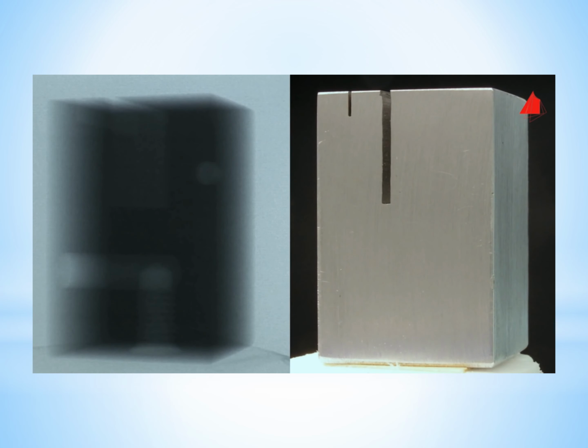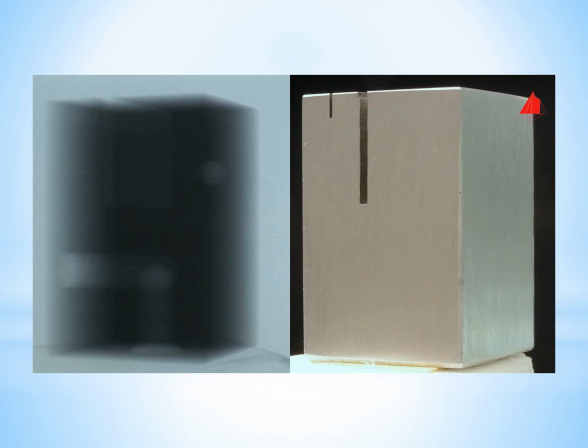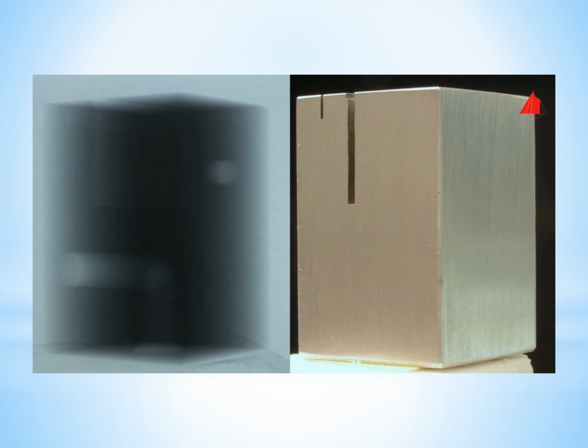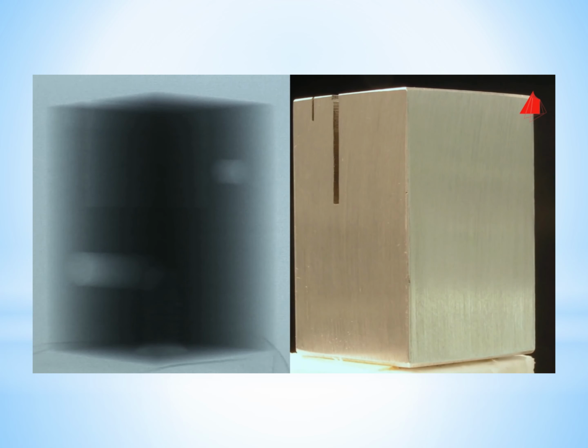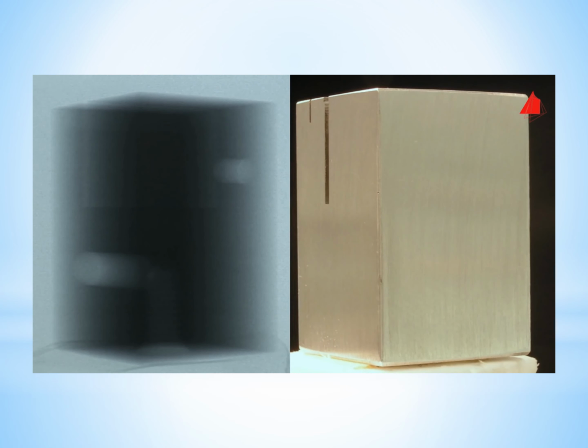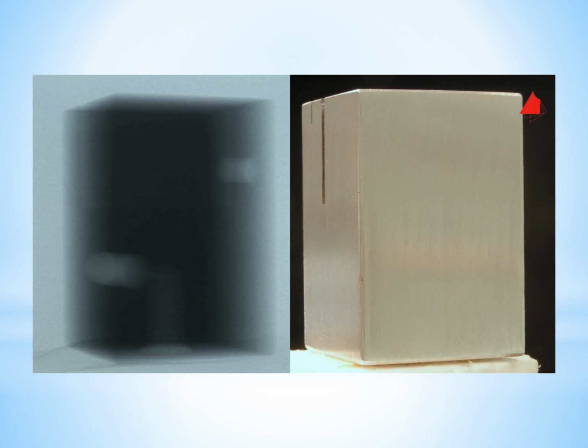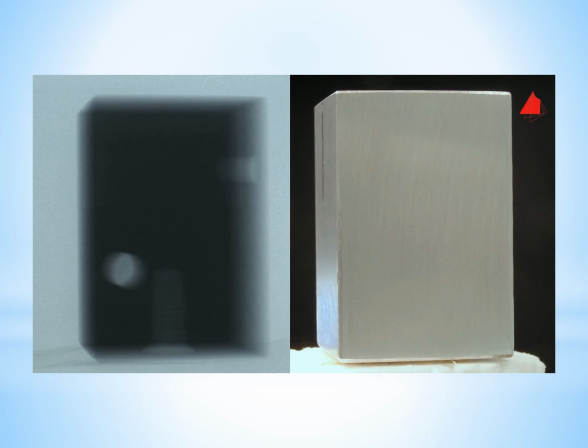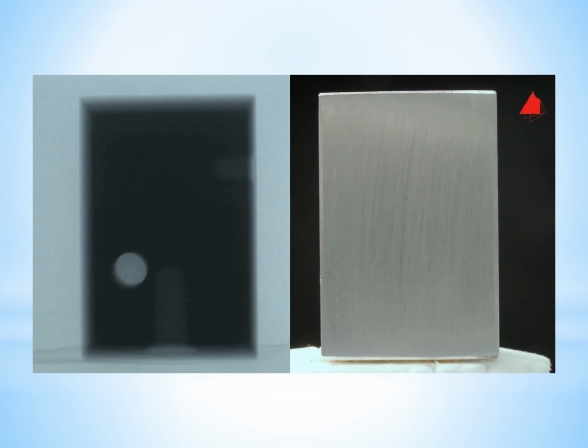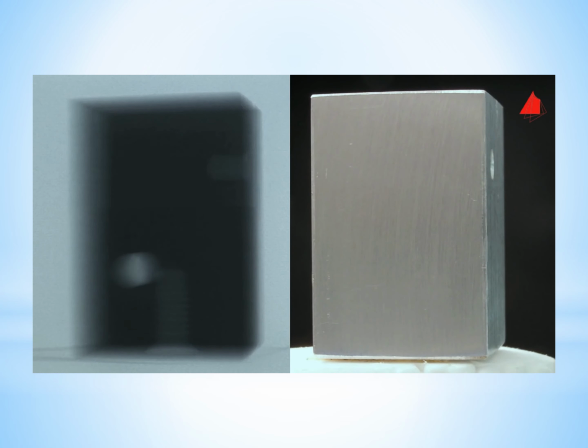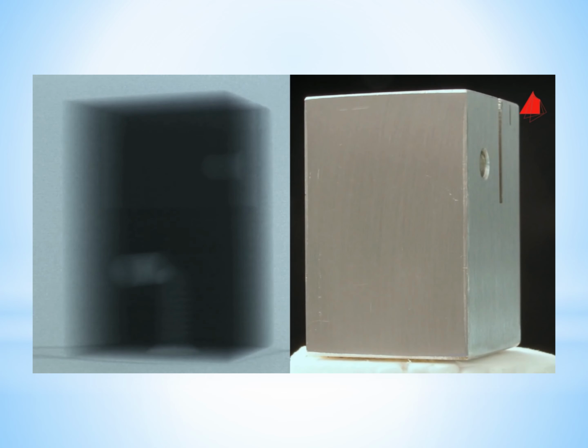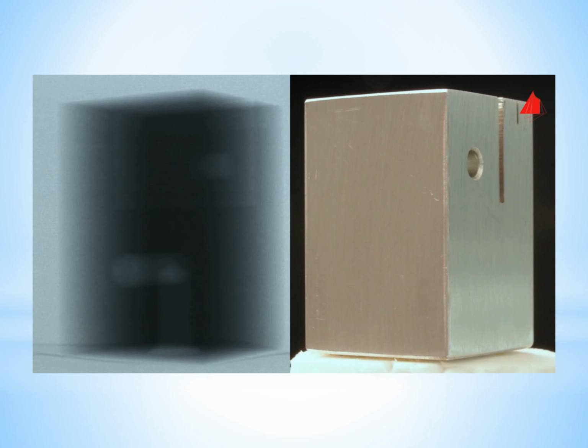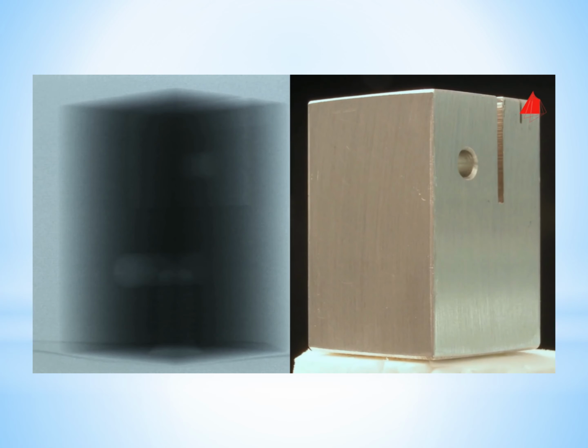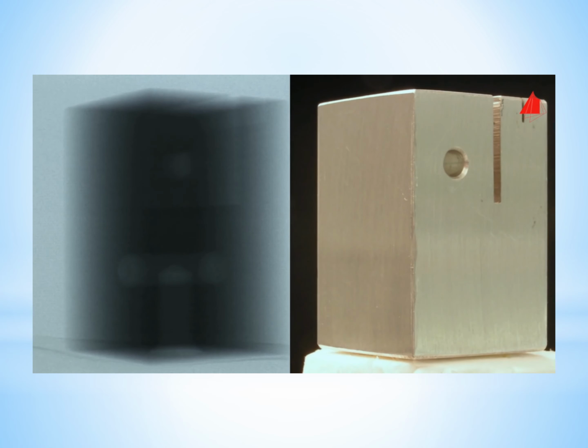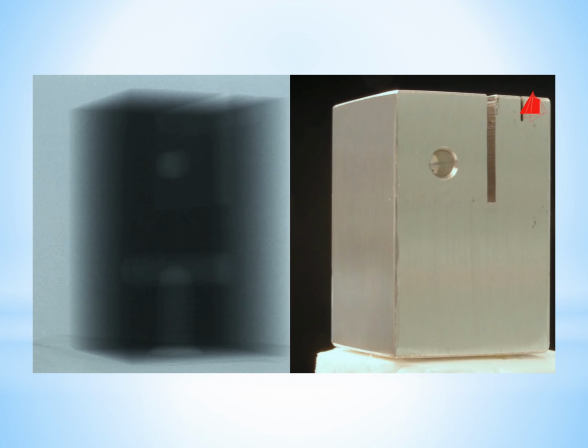In contrast to medical diagnostics, the X-ray tube and the detector field are both at rest, and the sample rotates. The X-ray images are displayed in real time on the computer monitor. As opposed to classical X-ray images, they are shown as positive images. Thick areas and areas free from defects now appear dark. Thinner regions or regions with defects appear light. The drill holes and the different saw cuts are clearly visible.